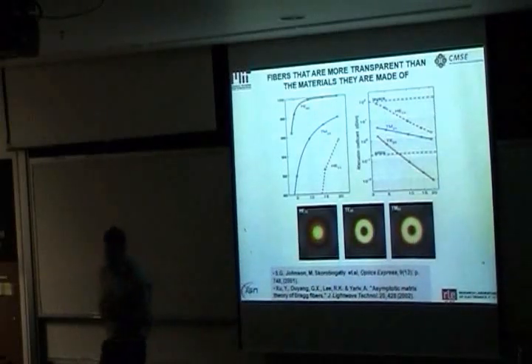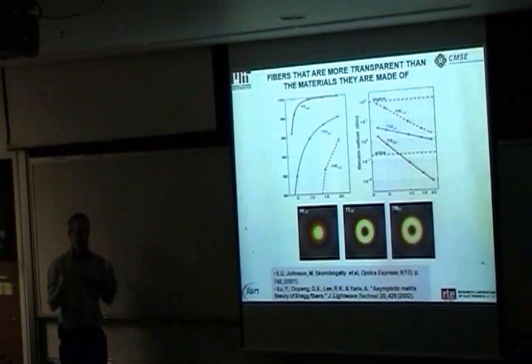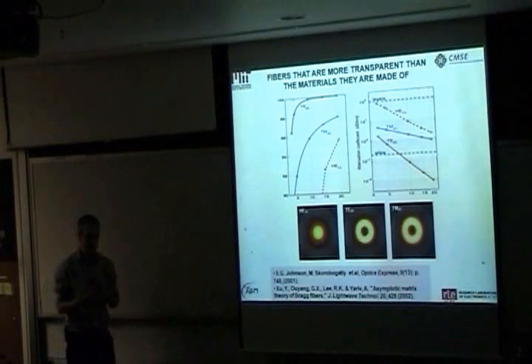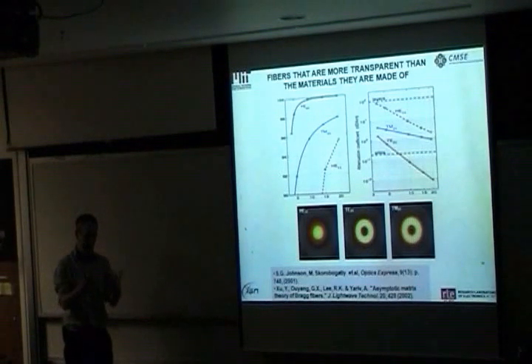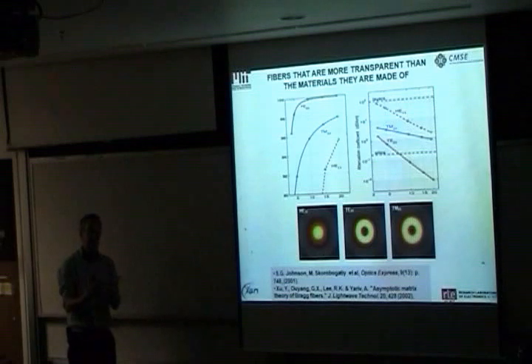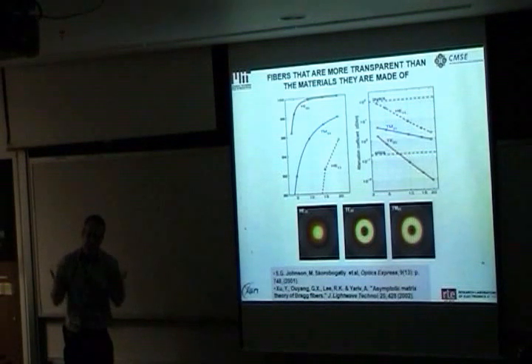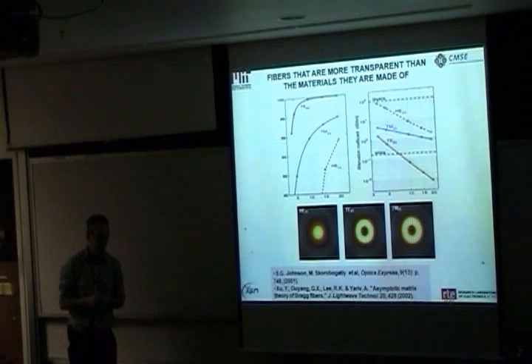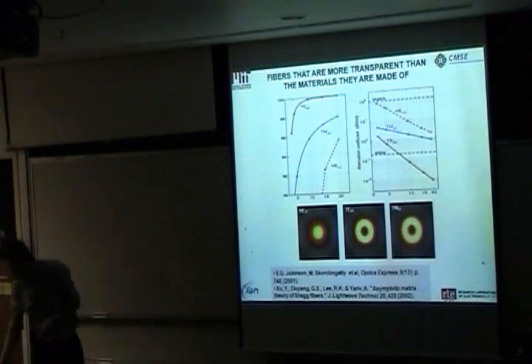The reason that was important is because for many years, since the advent of fibers, you were really stuck with a very small set of materials that could be made into fibers, that had sufficient transparency, and silica was obviously the most important one. But silica, even though it's transparent, is only transparent in certain wavelengths, and obviously above 2 microns, it's not very good.